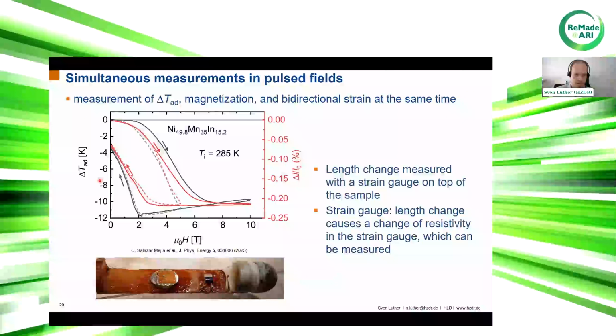You can see here in black the adiabatic temperature change for this nickel manganese indium alloy, where the initial temperature was 285 Kelvin. As you can see, we have a negative adiabatic temperature change, which means we can not only heat up, we can also cool down our samples by application of magnetic fields, for example up to 10 Tesla. And from the up and down sweep, we get a certain hysteresis. Quite similar behavior we see in the relative length change in red. So we also have a certain hysteresis by application of magnetic fields in our nickel manganese indium alloy.